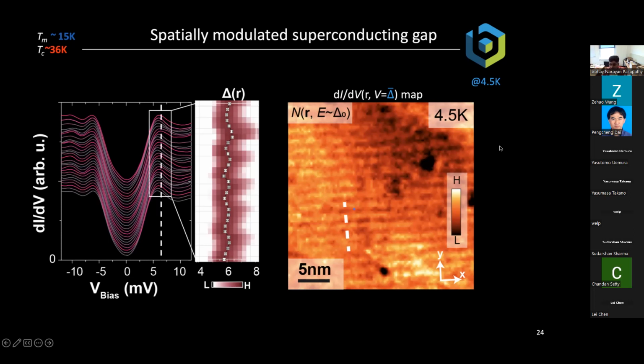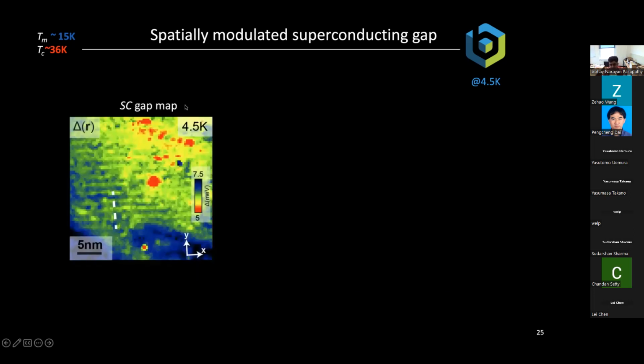Okay, so this was our first observation that the superconducting gap displays these modulations. And we wanted to make sure, A, that this has something to do with the magnetism in the material, and B, that it has something to do with the superconducting order in this material. And so in order to see that it really has something to do with magnetism and with superconductivity, we did a few experiments that I'm now going to describe to you. So first, just to say, we can actually plot out what the superconducting gap looks like in real space, and you can see the same modulation in the superconducting gap that you saw on the last slide.